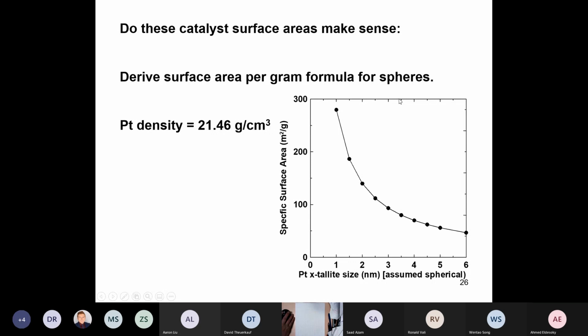Right. So we were talking about catalysts made from platinum nanoparticles, and we had a very simple formula that we derived for the specific surface area as a function of size. And I just want to show you that commercially available carbon-supported platinum catalysts are very close to what you would predict based on the simplest of equations, which was specific surface area equals 3 divided by rho r that we derived last day.